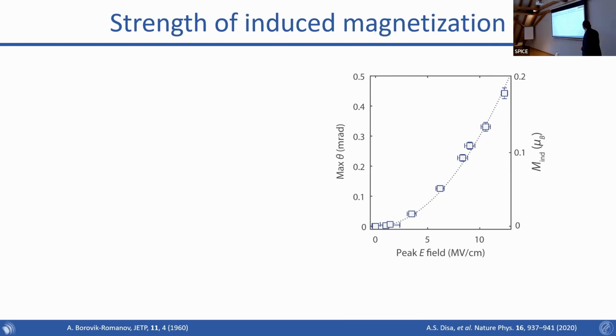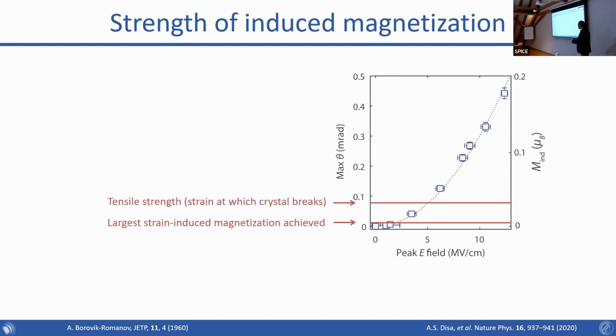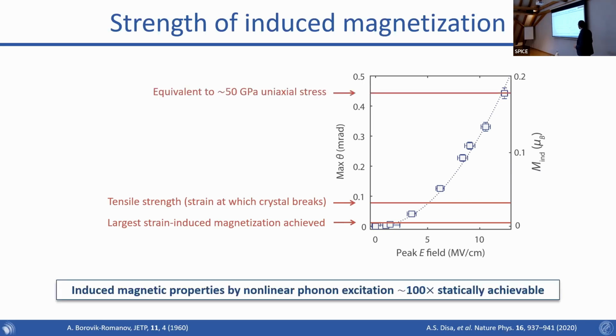And so we can compare this now to what can be done with strain. In the previous reports back in the 60s, the largest strain-induced magnetization that was able to be achieved is around 10 to the minus 3 Bohr magnetons per unit cell. So we can achieve obviously something much, much bigger than that. And in fact, if we even looked at what would happen if you stressed it as much as you could before the crystal broke, you'll get around 5 times 10 to the minus 2 Bohr magnetons per unit cell. So we're actually at a situation where we're almost 100 times more than what you could actually achieve statically.